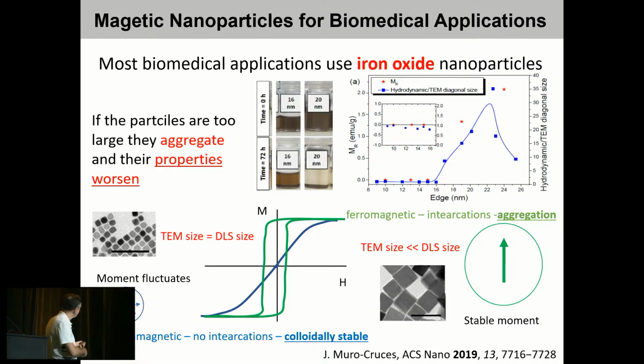And when the particles are larger, then the magnetic moment is stable. And then we have a typical hysteresis loop shown in green here. But what happens when the particles are large? Then at zero field, they have a large magnetic moment. That means that they can interact with each other magnetically by dipolar interactions. And the lowest energy state is that they agglomerate and form clusters.